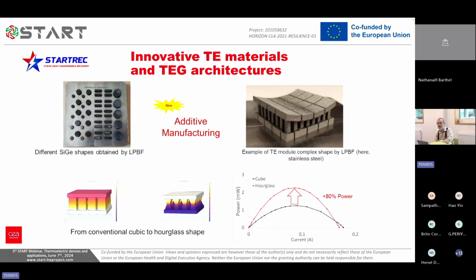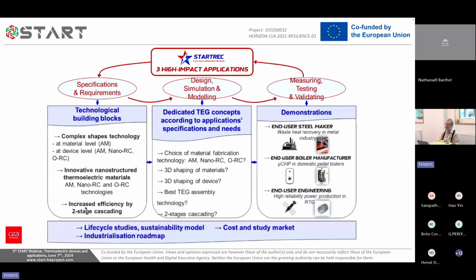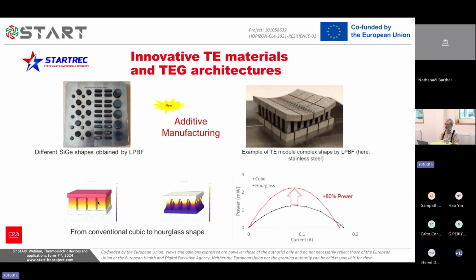Then the brand new additive manufacturing. So you see again a new design of a TEG, and on the bottom of the picture you see the results of some simulation. So this is simulation, it's not real, but the real thing we're going to do in STARTREC. So just by swapping from the conventional rectangular shaped legs, if you make this hourglass shape here, just by reducing the surface here in the middle, you increase the thermal gradient so much that the power factor increases by 80%. That's simulated. We want to demonstrate it.